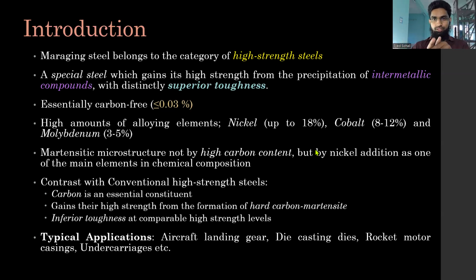You have a martensitic microstructure, but the martensitic microstructure is not from high carbon. The martensitic microstructure that we see in martensitic stainless steel, for example, or other steels, is hard because the carbon content is high. Here, we are seeing a martensitic microstructure, but it is not from high carbon content. It is from nickel addition as one of the main elements. Nickel is added as the main element, so that makes it different. And this martensite form is tough. It's not hard. So that's another difference that we see.